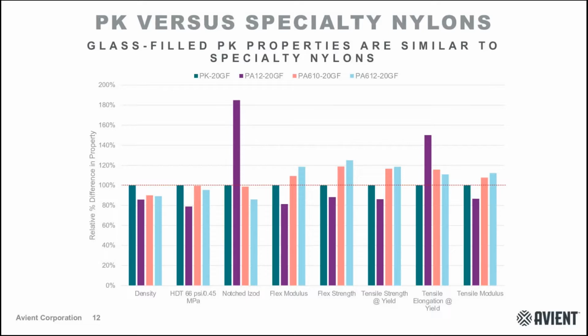Let's talk a little bit about specialty nylons. In this case, we're not doing a dry as molded to moisture conditioning compare. We are just comparing the properties of glass-filled polyketone to that of 3 different grades of specialty nylons, nylon 12, nylon 610, and nylon 612, all loaded with 20 weight % glass fiber. And so here, the dashed line at 100% represents the properties of polyketone, and then we're looking at how these properties of the specialty nylons compare.